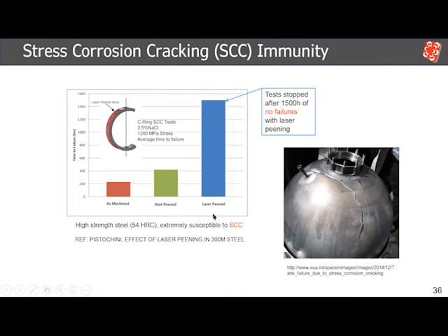So again, like a lot of the original data, laser peening and shot peening were investigated to improve the life of the baseline here. In this case, is as machined. You can see the as machined condition, the life from these testing was around 200 hours. Shot peening was able to generate an improvement, pushing the life of that sample up to 400 hours. Laser peening was able to run up to 1,500 hours without failures. So the testing was stopped after 1,500 hours and no failures were detected.